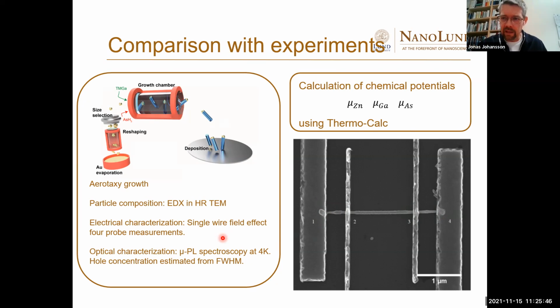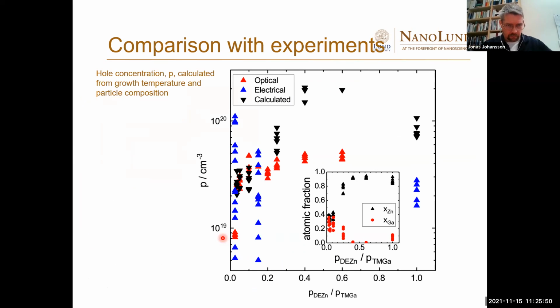So let's compare with experiments now. Here we see the hole concentration, the peak concentration, as a function of the pressure of diethyl zinc divided by the pressure of gallium. And the inset shows the atomic fraction of gallium and zinc from the measurements. So these values here, plus 1% arsenic, will be my inputs for calculating the chemical potentials, which will lead to a doping concentration. So it's a sort of semi-empirical calculation with no fitting parameters. I don't count the arsenic as a fitting parameter because the result will not vary much with arsenic anyway.